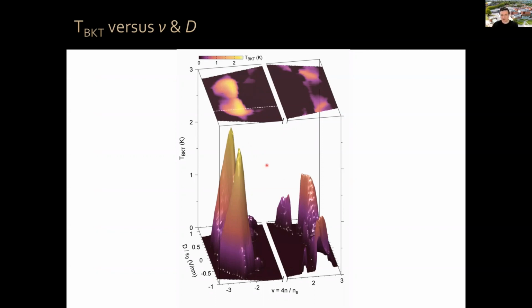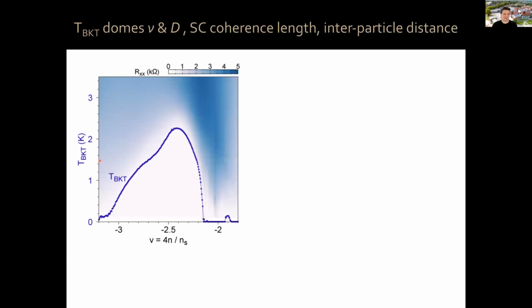Now, because it's always a little bit complicated to look at color plots, let me show you a trace at optimal electric field, TBKT at optimal electric field versus filling factor, and also a trace at optimal density versus electric field. Again, this system is very highly tunable, so we have many knobs, okay? So this is TBKT, this blue trace, as a function of filling factor at optimal electric field. As you can see, there is a small superconducting dome in TBKT here when you dope with electrons with respect to the 2 holes per moiré unit cell state. And then there is a bigger superconducting dome here for when you add extra holes.